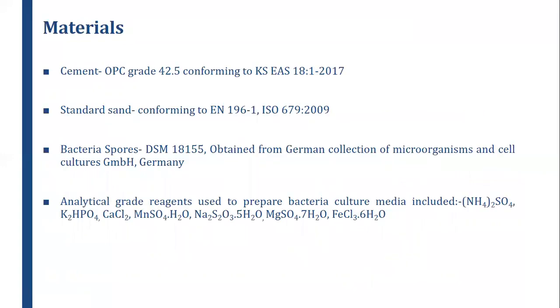The materials involved in this experiment were ordinary Portland cement, grade 42.5 conforming to Kenyan standard, and standard sand conforming to EN and ISO. Bacteria spores for this experiment were obtained from the German Collection of Microorganisms and Cell Culture, whereas the analytical grade reagents were locally purchased to prepare the bacterial culture. The reagents used included ammonium sulfate, potassium phosphate, calcium chloride, manganese sulfate, sodium thiosulfate, magnesium sulfate, and